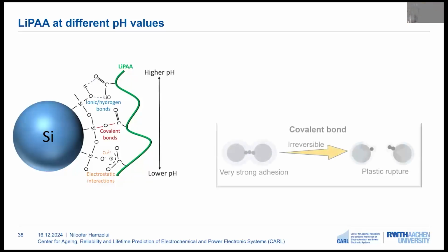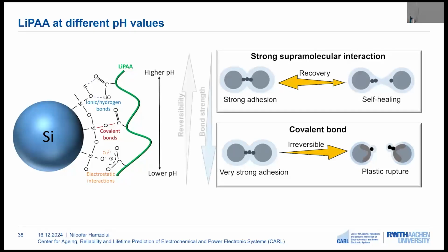Also, if we have a look at different pHs, it can be seen that at lower pH, we can have the formation of stronger covalent bonds, which is more irreversible, and it can result in plastic rupture upon charge and discharge. And then with increasing the pH of the binder to more neutral pHs, we are having stronger supramolecular interactions like hydrogen bonding and ionic bonding, which will also have recovery after a huge volume expansion of silicon.